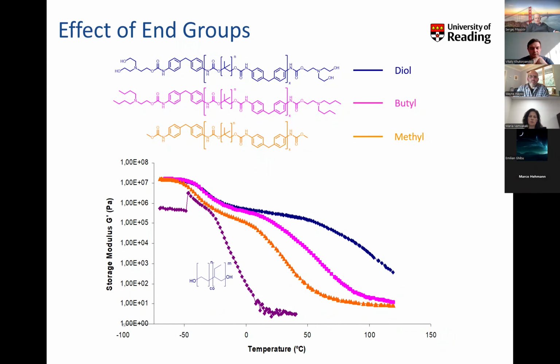When we analysed these supramolecular polymers via rheology, what we quickly realised was that these materials have some very interesting characteristics. Now, we're never going to really use a hot melt adhesive below zero, but since we were able to with the rheometer, we studied these compounds across the temperature range shown, from below -50 up to 150.